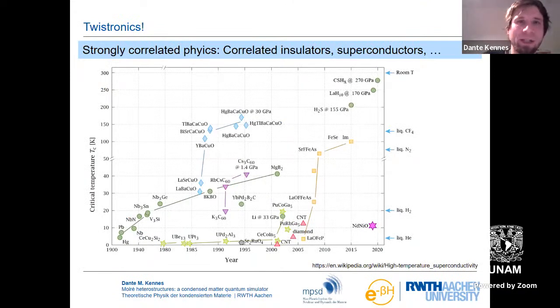All right, so why is this interesting? Well, I think this really became interesting when people looked at these twisted bilayers of graphene and found signatures that hinted at effects of strong correlations. Of course, one of the driving themes in condensed matter physics for quite a while now has been to find better and better superconductors. So again, this is a graph that I shamelessly stole off Wikipedia. What you see is the year of discovery of this material on the x-axis, and then for all these superconductors, the superconducting temperature, when these systems turn superconducting, is on the y-axis. And of course, up here is room temperature. We have these very recent results on systems under immense pressure that apparently exhibit very high TC. These are interesting because they approach this room temperature limit, but they are not at ambient conditions. We, of course, want to be close to ambient conditions for devices.